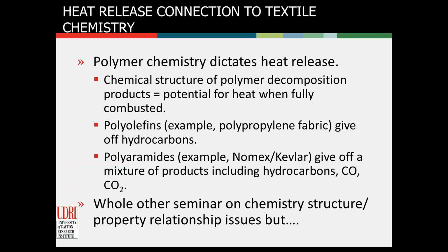Polymer chemistry, or I should say material chemistry, will dictate heat release. So I mentioned cotton, which is not really a polymer, but is a natural cellulosic material. It's got its own chemical structure. It wants to char, it wants to smolder. That's a function of its chemistry. Polyesters, polypropylene, polyethylene type fabrics don't want to char, although some polyesters do, but for the most part they don't, and they melt and flow.